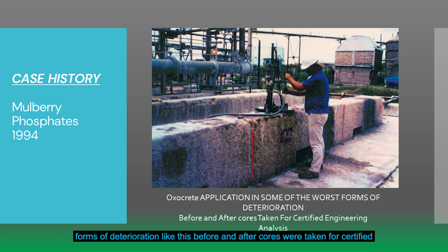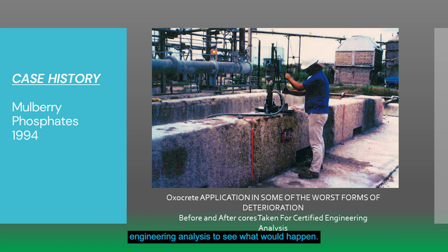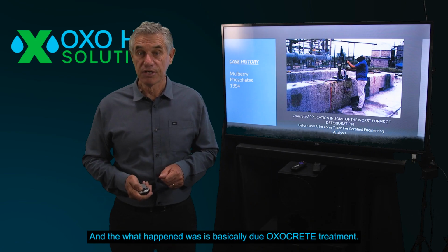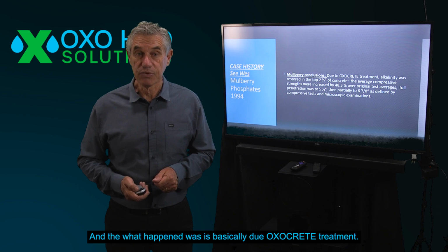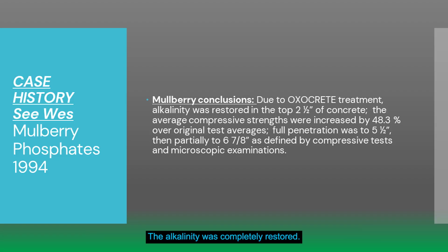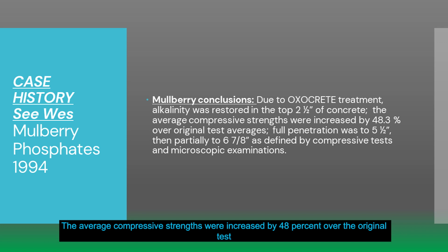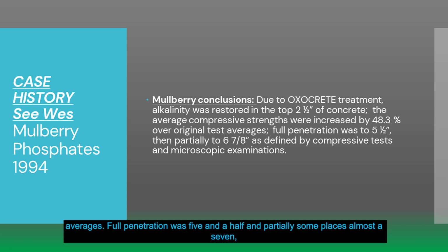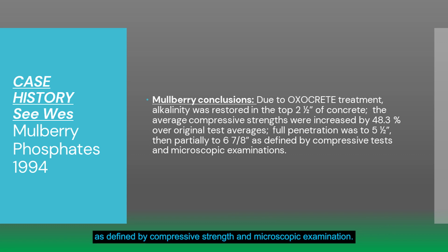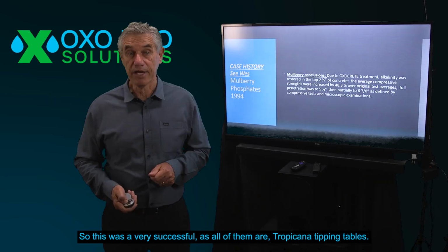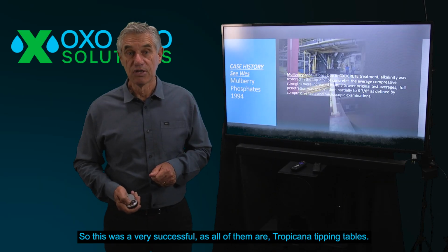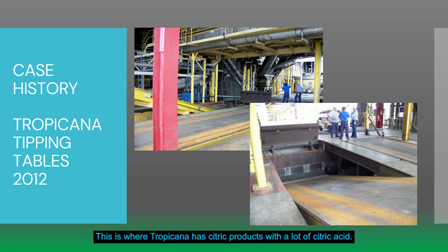The OXOCRETE application on some of the worst forms of deterioration like this. Before and after cores were taken for certified engineering analysis to see what would happen. And what happened is that, due to the OXOCRETE treatment, the alkalinity was completely restored. The average compressive strengths were increased by 48% over the original test averages. Full penetration was 5.5, and in some places almost 7, as defined by compressive strength and microscopic examinations. So this was very successful, as all of them are.